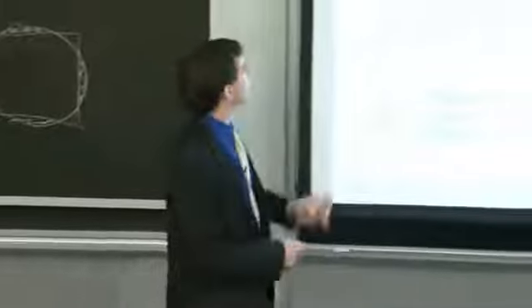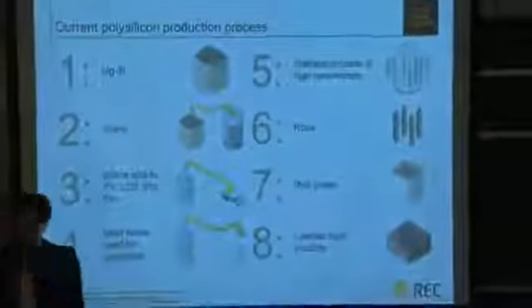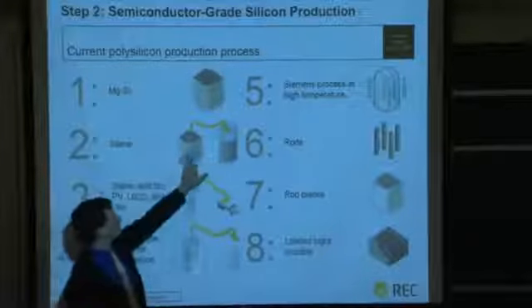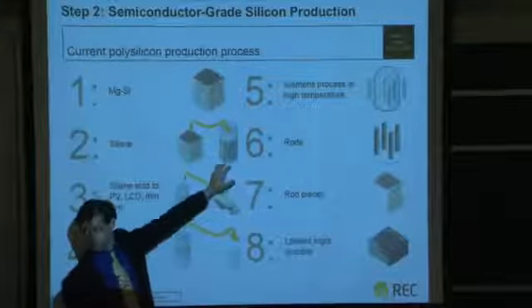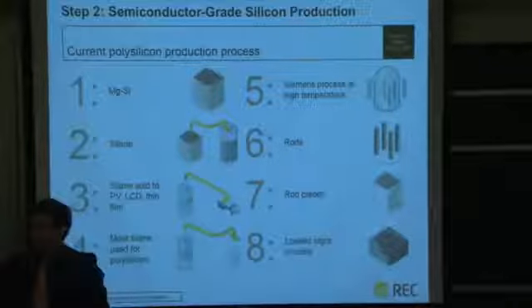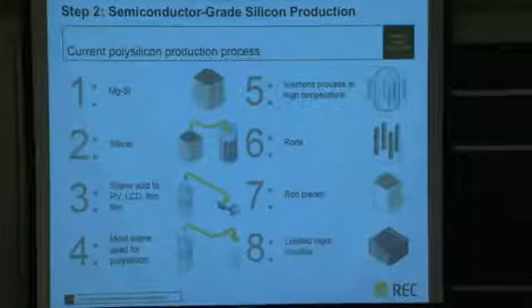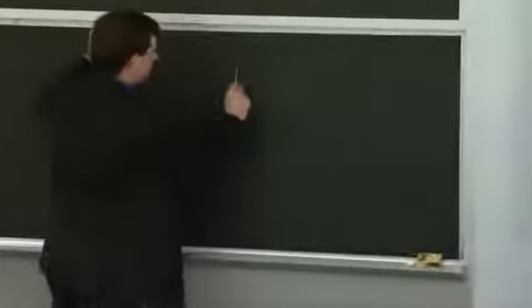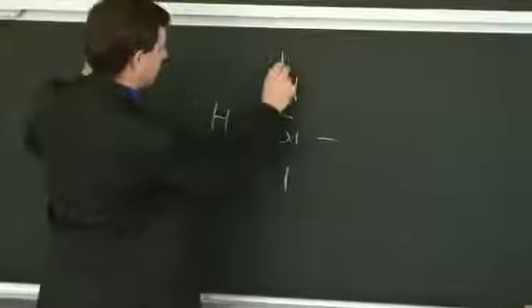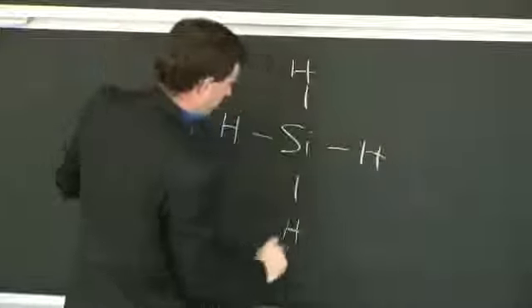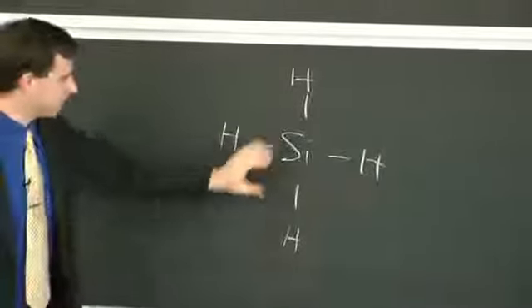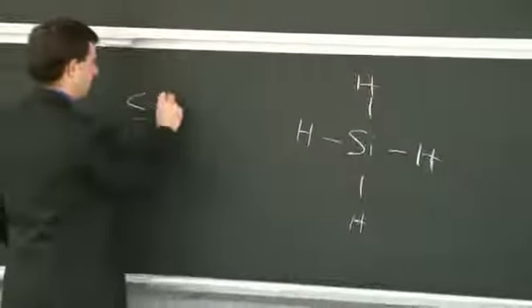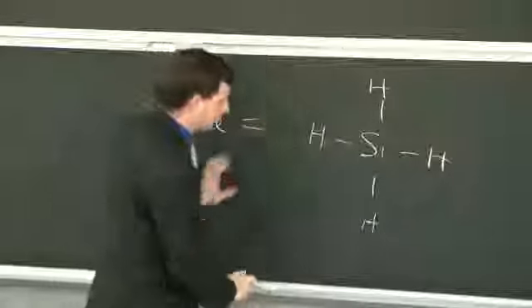So the way this process works is we start with metallurgical grade silicon at the top, represented by a little sack of metallurgical grade silicon chunks. We produce silane gas out of that metallurgical grade silicon. Silane gas is SiH4. So it'd essentially be this right here. You'd have a silicon atom here, tetrahedrally coordinated, tetrahedrally meaning 4 bonds, with hydrogen atoms on the side. And this is silane, which at room temperature is a gas.